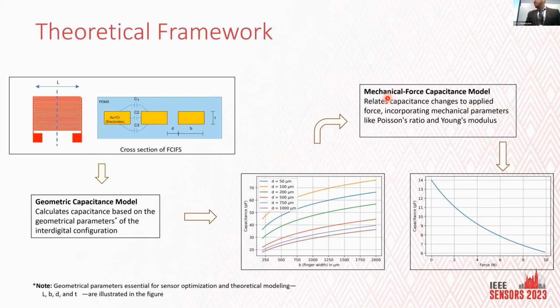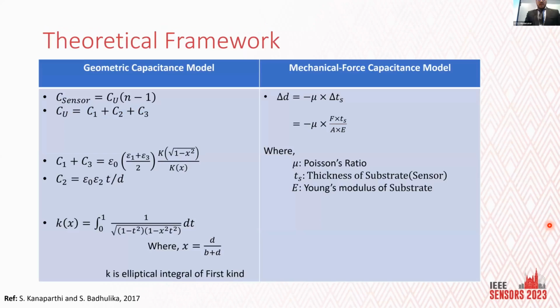We have basically come up with two very simple models. First is a geometric capacitance model, and the next is a mechanical force model. In the geometric capacitance model, we find the initial capacitance of our sensor using some set of equations. I will talk about those equations in the next slide. So the dimensions, the width of the electrodes, the gap between the electrodes, and the dielectric of the material, we feed into the geometric capacitance model, which will give us curves for different widths and gaps. From these curves we can find out what capacitance range we want to operate in. This will then be fed into the mechanical force model, which will give us force versus capacitance. Now I will talk about this model in detail.